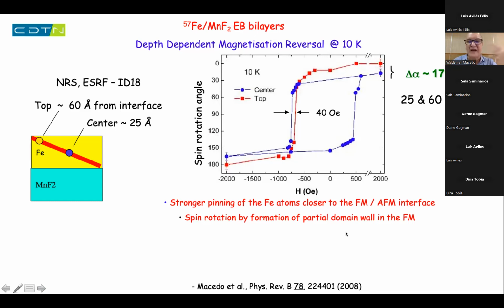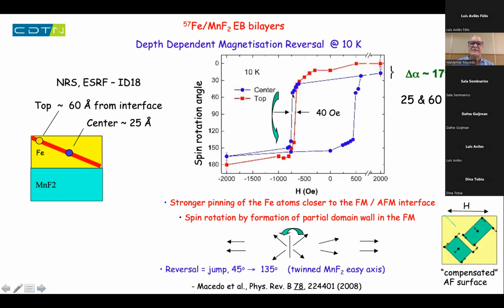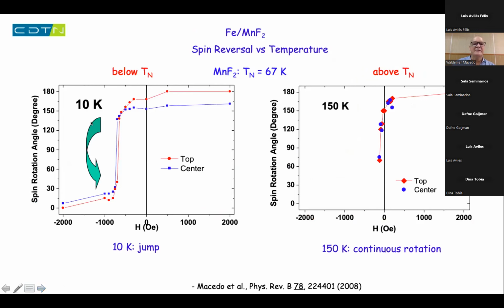This is a clear sign of the stronger pinning closer to the interface, and the rotation is like a spring magnet. And you see also the reversal below the Néel temperature: you have this jump of the spins from one direction to the other direction of the antiferromagnetic spins of the fluoride. You see this jump below the Néel temperature, but you don't see it above the Néel temperature. That really is a signature that the spins of the antiferromagnetic material play an important role in these samples.